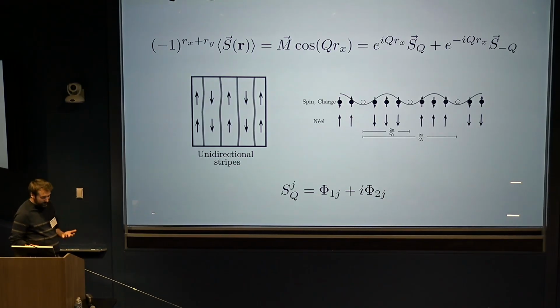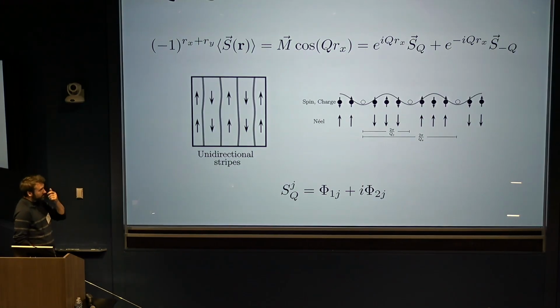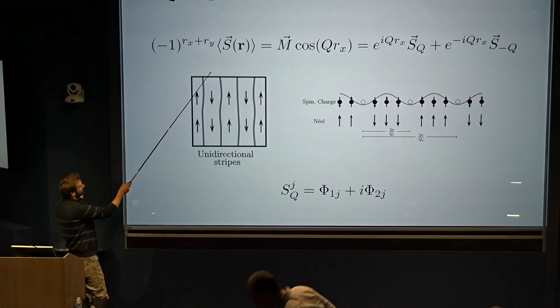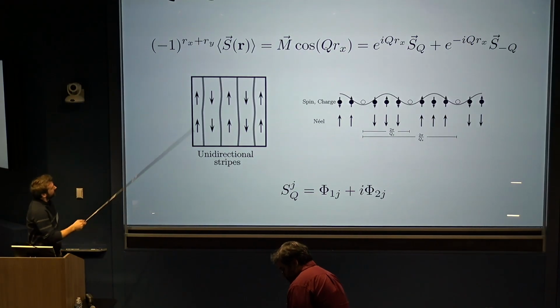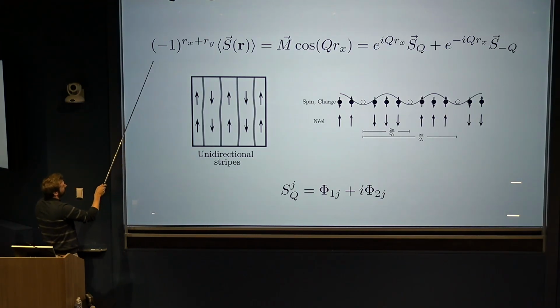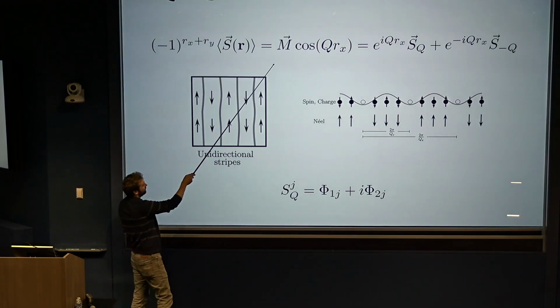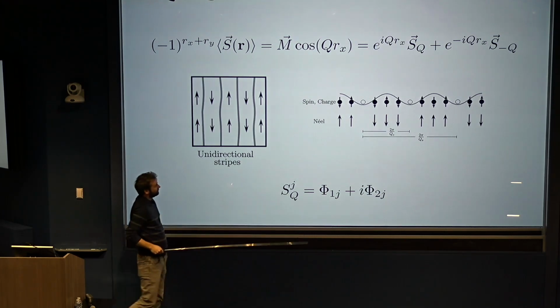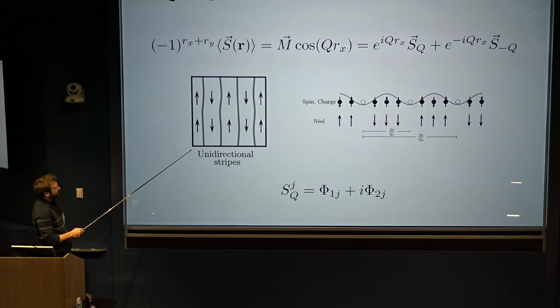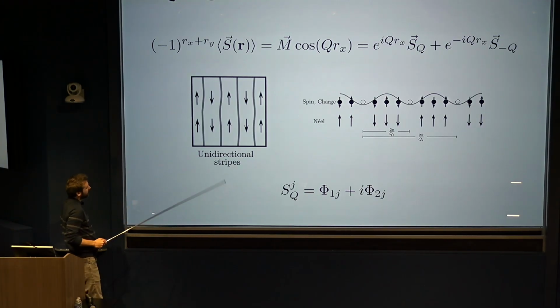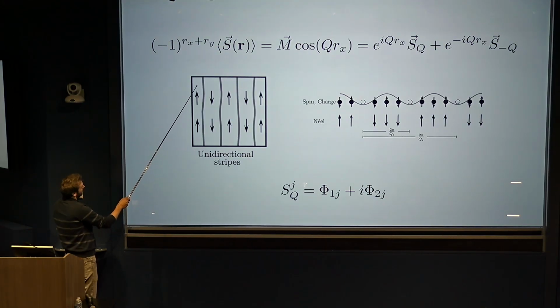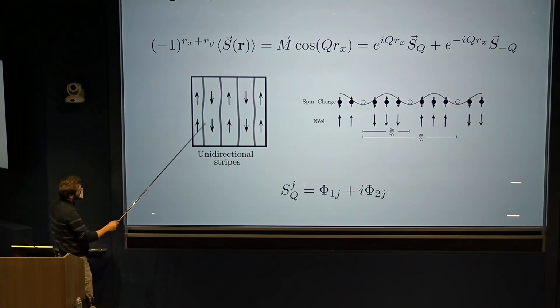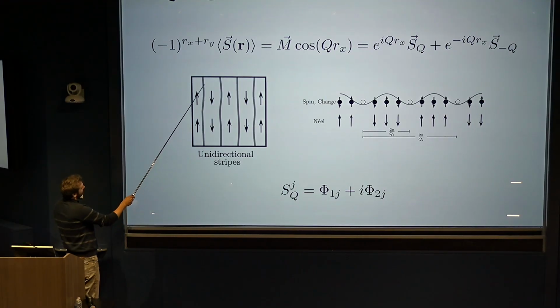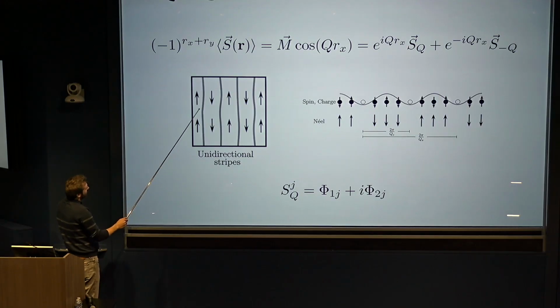And so here I will be thinking about these spin stripe orders. And in their simplest form, you can describe them with the following order parameter. So if you just calculate the local expectation value of the spin, and you isolate this fast oscillating antiferromagnetic sign factor here, then what remains in the simplest spin stripes is just a single cosine, so a single standing wave. And so what you get is a magnetic pattern where, if you plot this, this is the direction of the Néel order, right? Then it has these one-dimensional extended regions where it's basically non-zero. And in between those regions, the antiferromagnetic order goes to 0. And whenever you cross these gray lines, which is where there is no antiferromagnetic order, the direction of the Néel order actually changes. So you have up, down, up, etc.